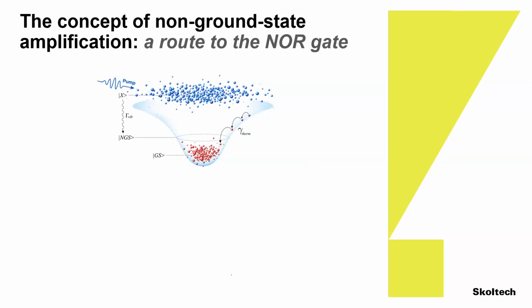Okay, so then what we did, we tuned our system in order to have the non-ground state, where the control beam comes not at k equal to 0, but at a small angle and slightly higher energy. And we tuned the pumping beam so that we can create an exciton reservoir where the one vibron is not exactly above the ground state, but from a non-ground state condensate. And now the experiment becomes actually quite trivial. If you do that, and of course, the fact that you are not dealing just with a parabola, but polaritons can move in the plane in 2 directions, you deal with a paraboloid.